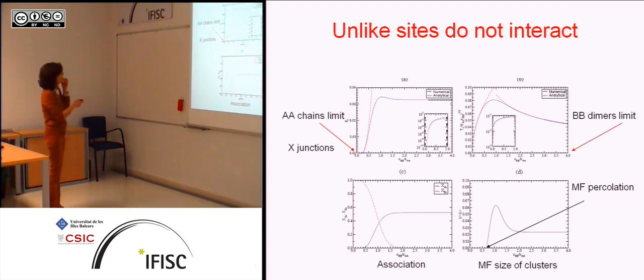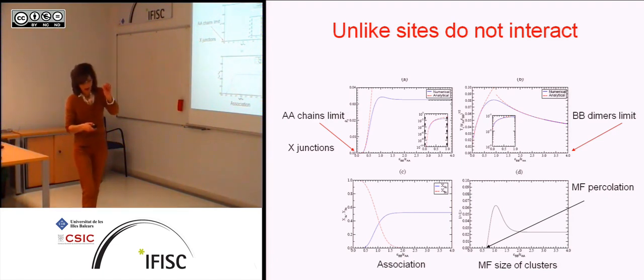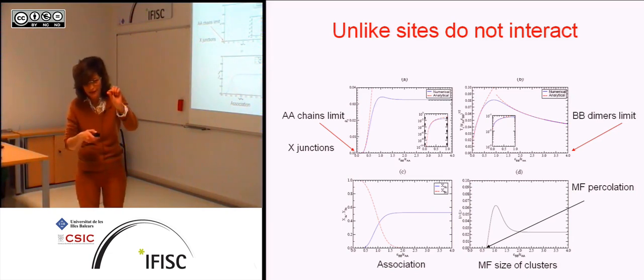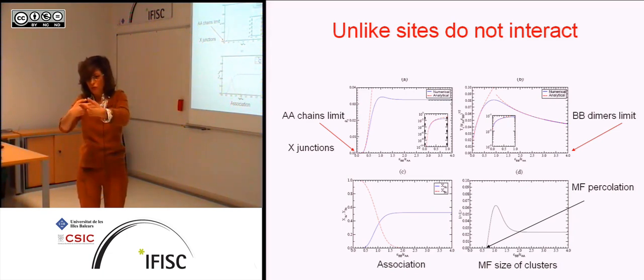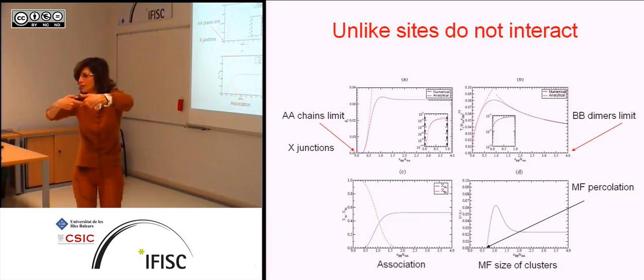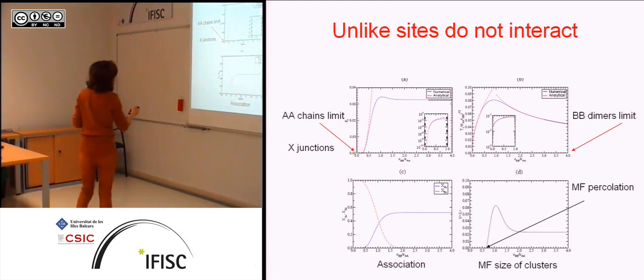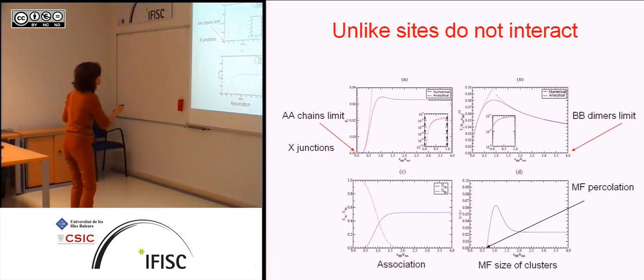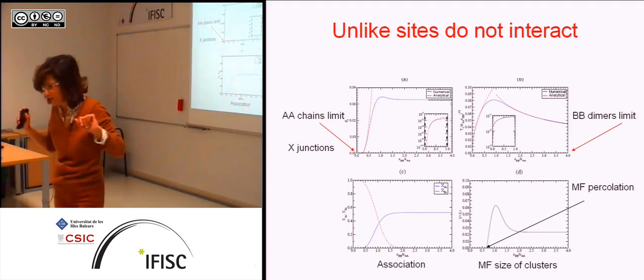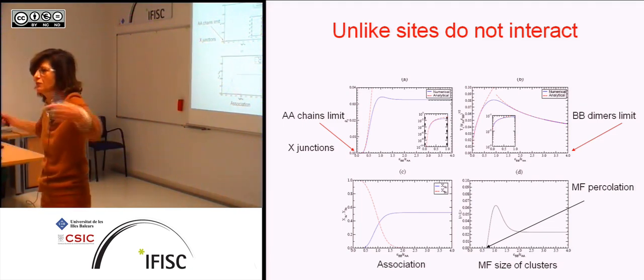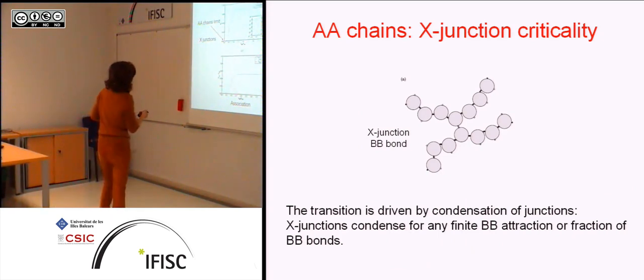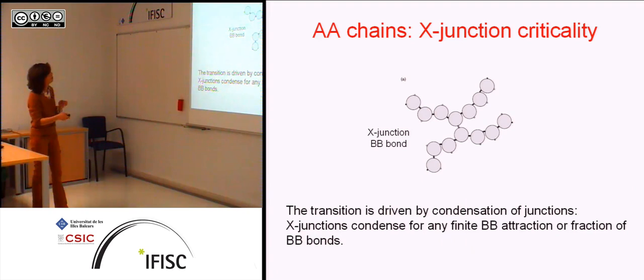So if we look at the chain limit and we switch off the BB interactions, we see that the critical point exists as long as you switch on those interactions. And if you think of chains that can bond through B bonds, they form an X-like junction. So we call these X junctions, and they go down to zero in terms of critical temperature and critical density. In polymers, the critical density goes to zero when the polymer chain length goes to infinity, just because of packing considerations. Forget the next two. So these are the types of chains we find when we look at the B bonds. So the transition is a normal transition, driven by condensation of X junctions.